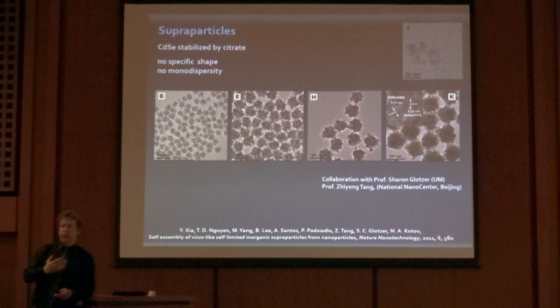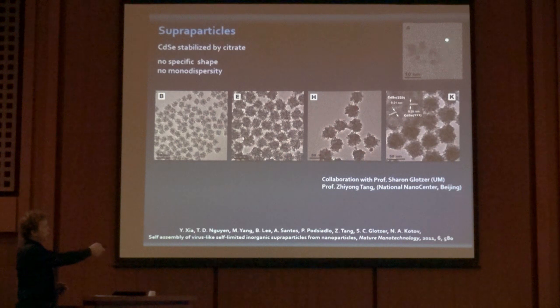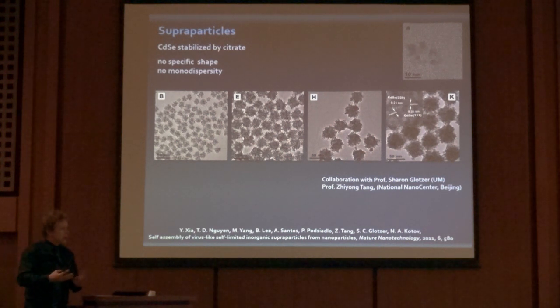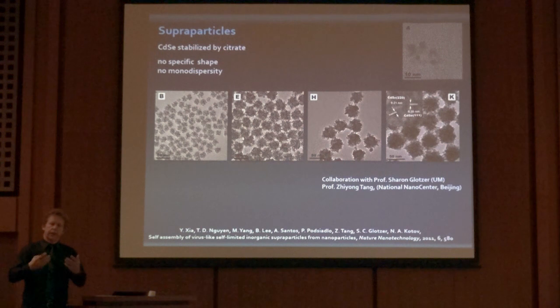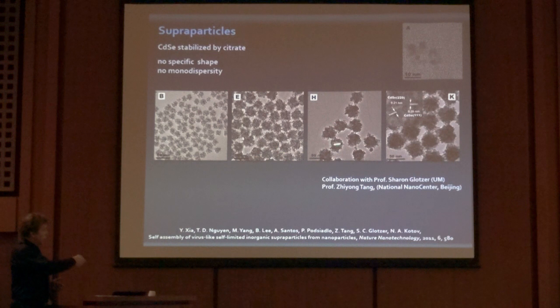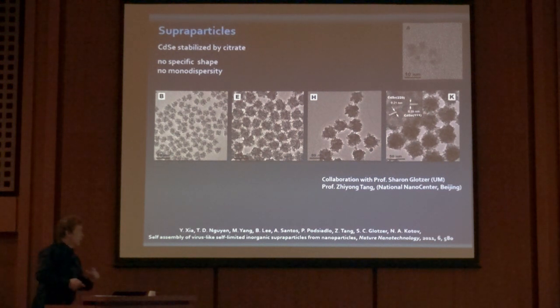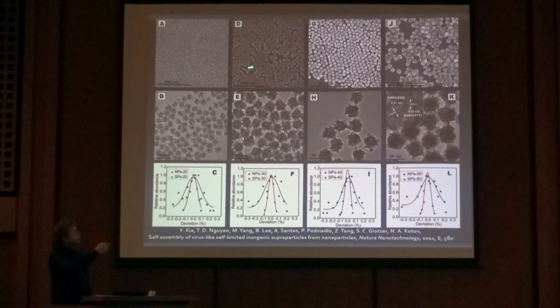They're actually in many ways ugly particles. They are of high polydispersity. They don't have any particular shape. They basically can be made in the kitchen. And we observed that they spontaneously form this monodispersed superparticle assemblies, and in addition to the transmission electron microscopy, we can appreciate their monodispersity on scanning electron microscopy.